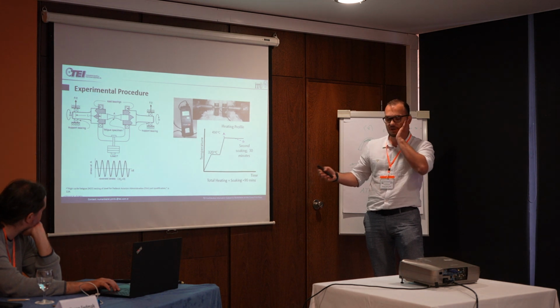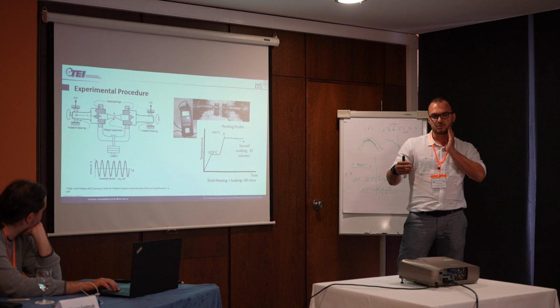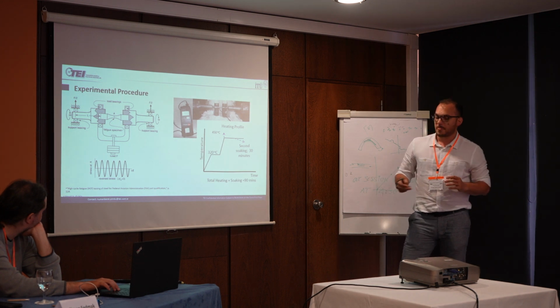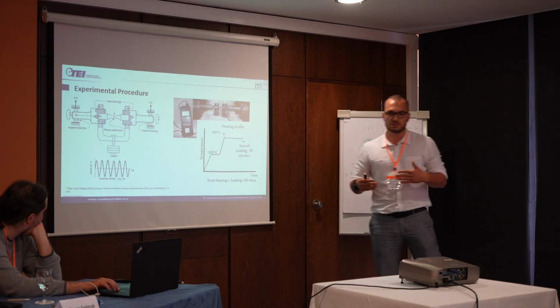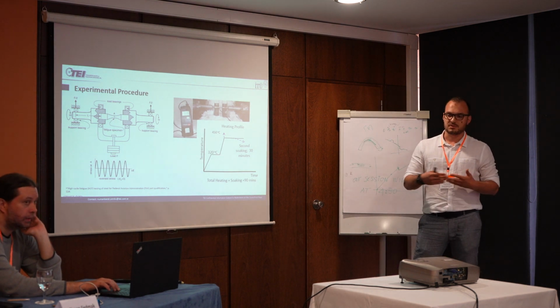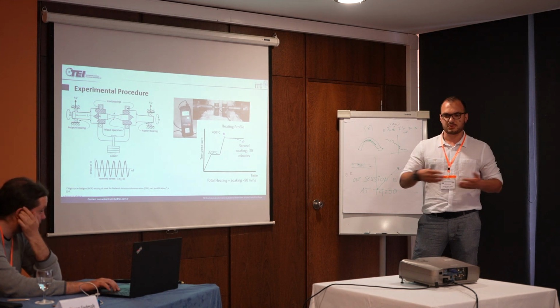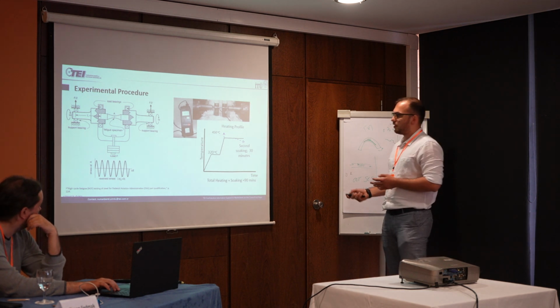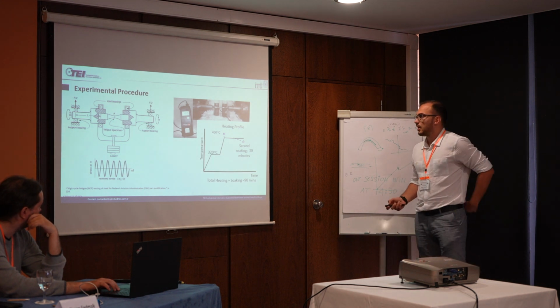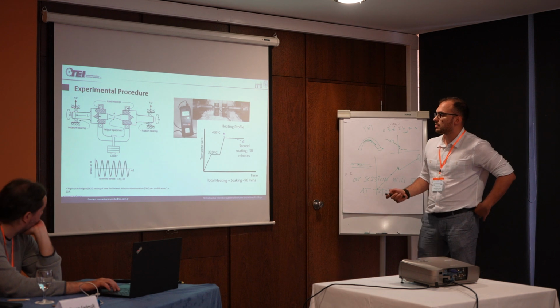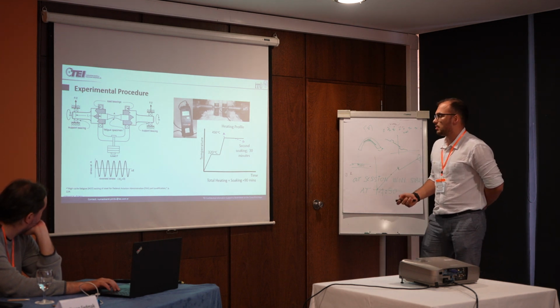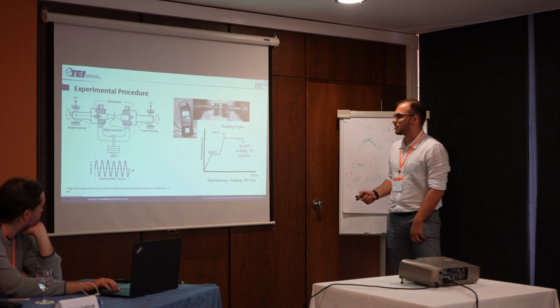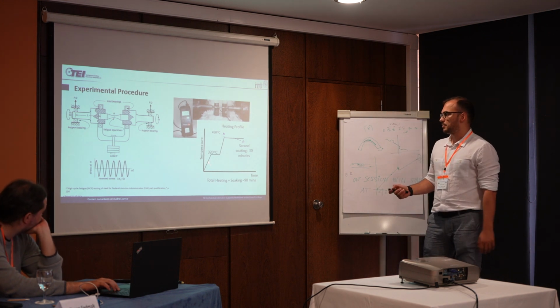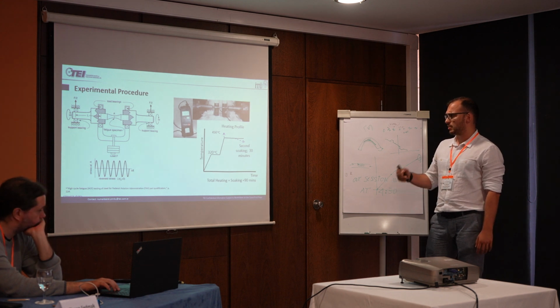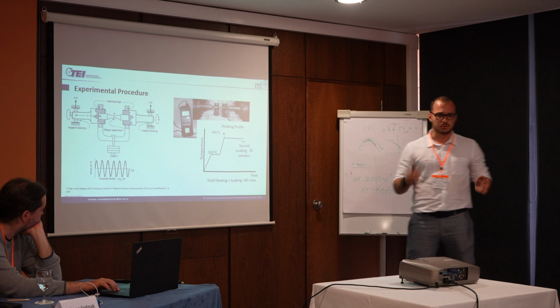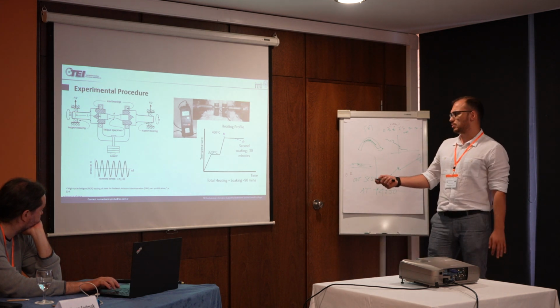I mentioned that we performed a high temperature test too. In that case, in order to make sure we have the correct temperature at the specimen, we performed some temperature profiling before the tests. After the temperature profile, we saw that the best way to reach the testing temperature, which is 450 degrees, is in 2 steps, and between these 2 steps we apply some soaking time in order to homogenize it, and so on.